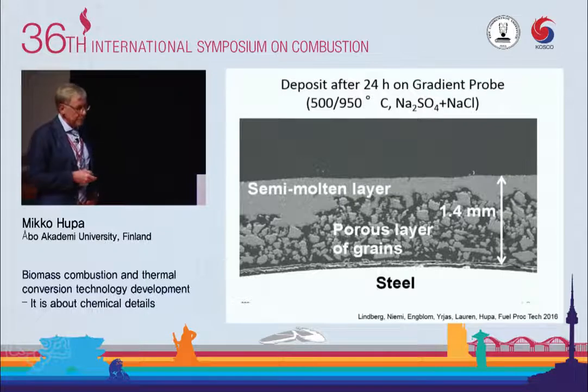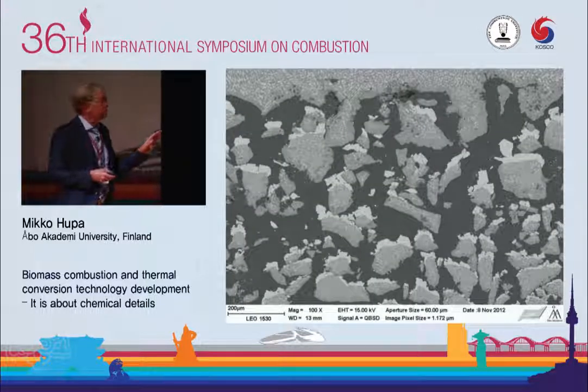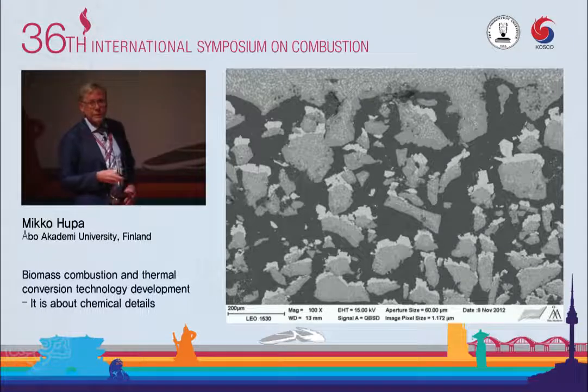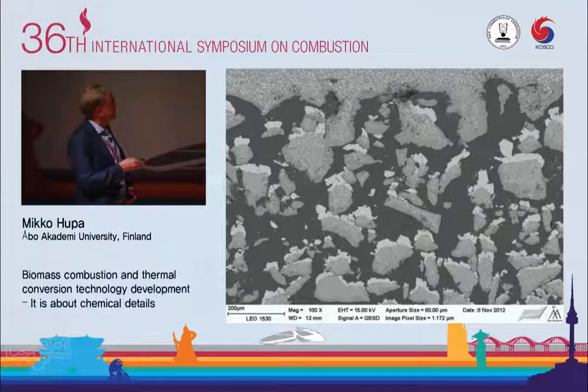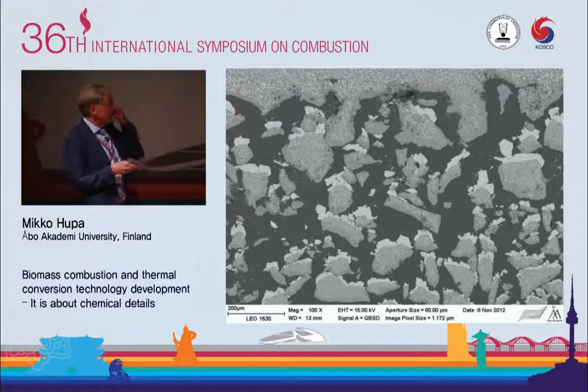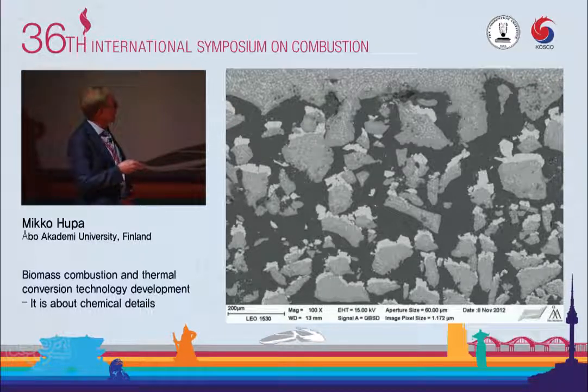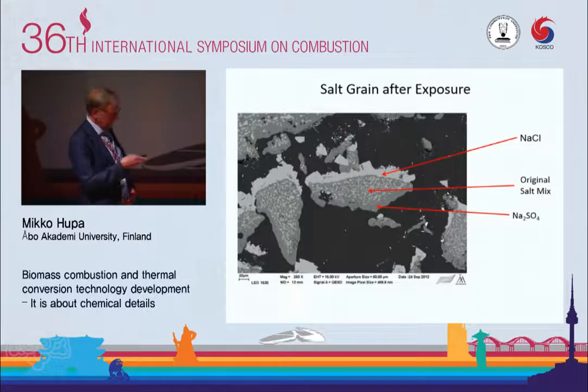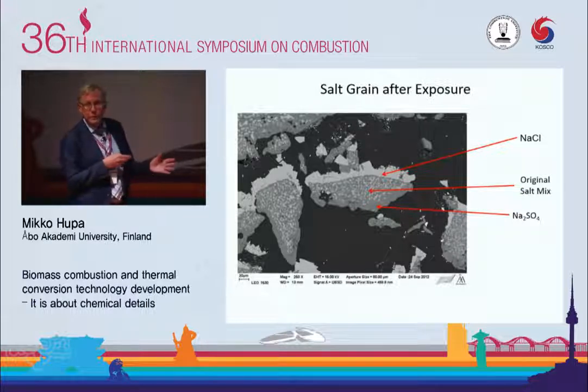But if we take a closer look into this, we start seeing that also the type of the particles have changed. The particles didn't look like this when we put them in. So now they have this white layer on top. And if we take one more close-up, we can see that, yes, each particle has received this white layer of material, and also the lower part looks different. Now, the center of this particle shows how they looked before, at the beginning, original salt mix.